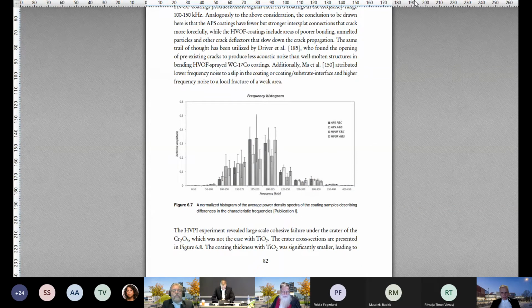And what does it mean? I had an identical question myself. Yeah. Another way of trying to quantify difficult results of the acoustic emission in this case. What it means is, after the fast Fourier transformation, we get the amplitude of different frequencies that we hear during the test. And because it's a continuous line, I wanted to bin them somehow. Like here, first it's 50 kilohertz, that we have this many between 0 and 50, this many between 50 and 100, to get to the severity of the individual cracks.